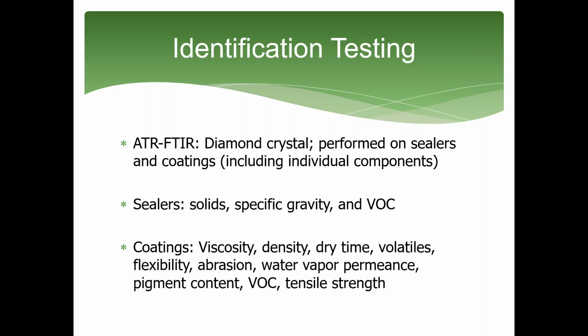I'd like to talk about the identification testing. It's also called fingerprint testing. It's performed to ensure that the qualified product is consistent with the product delivered for service. The FTIR is the infrared scan that is performed on individual components if the liquid coating material is a multi-component, as well as the mixed material, or if it's a single component material, the FTIR is run on that material only. Both sealers and concrete coatings are tested by FTIR.